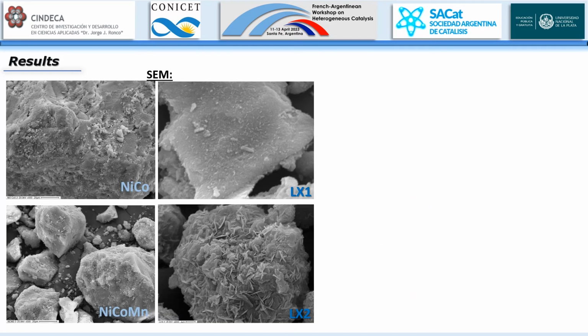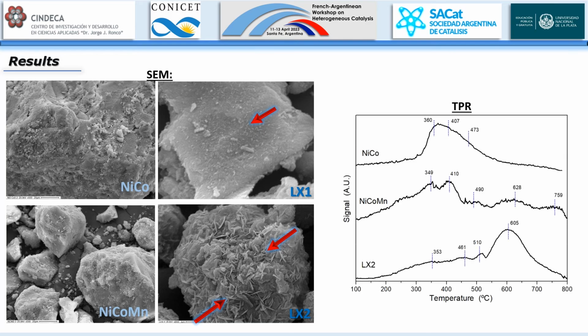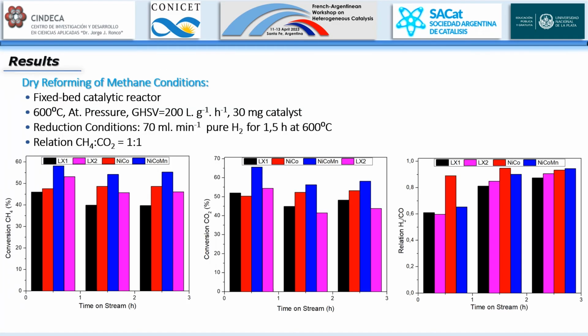The scanning electron microscopy showed significant differences in morphology, where the catalyst prepared with leached solutions presented peculiar filament structures over its surface. TPR studies were conducted and showed that at 600 degrees a good proportion of nickel was reduced. The dry reforming test conducted at 600 degrees showed comparable levels of conversion between the leach and the commercial salt catalysts. The hydrogen to carbon monoxide ratio obtained was about 0.9 in the 3 hour test.